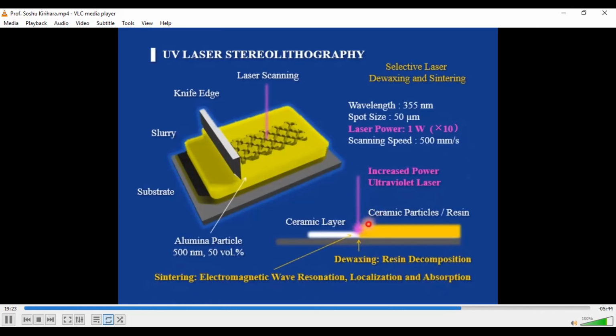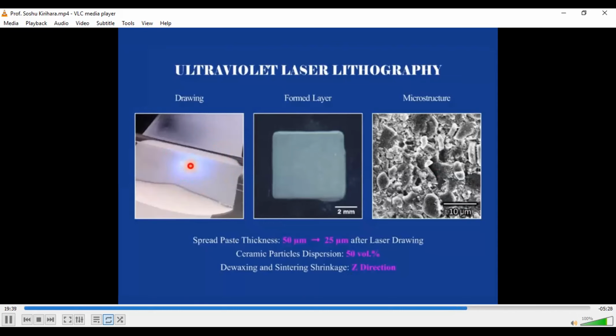Here is the ceramic paste material. After the dewaxing and sintering process, the remaining ceramic particles were sintered and create plate-shaped structures on the substrate. This figure shows the laser drawing process, and the bright color is the laser spot. After laser scanning, we can create plate-shaped materials like this. Here is the microstructure. You can see micrometer-order bulks created in the microstructure, about 5 to 8 microns. At first, the ceramic particle size is under 1 micrometer, so the micrometer-order bulks were created by laser beam irradiation.